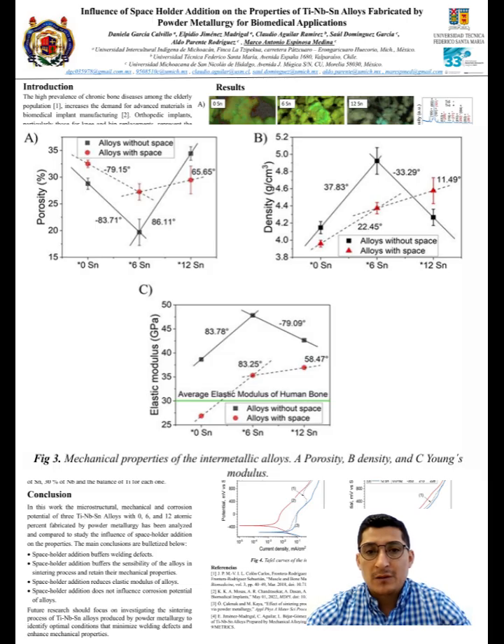The calculated values of porosity for the alloys sintered with the spaceholder agent are higher than the values for the alloys sintered without the spaceholder agent. Consequently, density and elastic modulus of this group of alloys are lower than values for the group of alloys sintered without the spaceholder agent. The inclination of the lines between calculated points for the alloys sintered without the spaceholder agent is larger than the inclination of the lines for the alloys sintered with the spaceholder. It suggests that the space-holder agent buffers the sensitivity of the alloys to the sintering process.